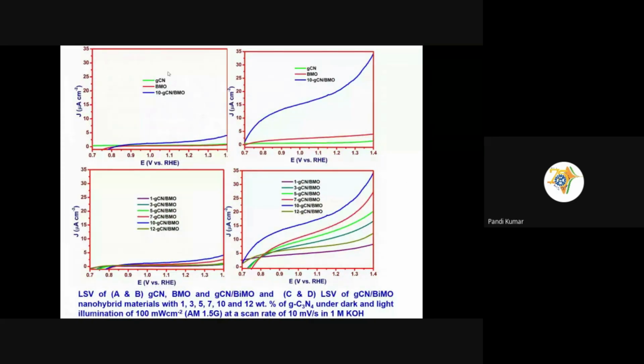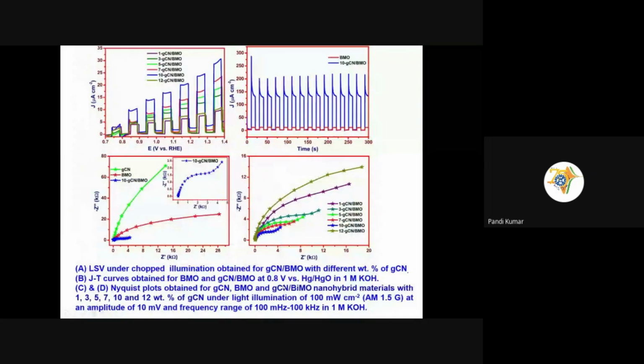So we have done the characterization in the absence of light. Just look at this. This is the control sample, and this is the variation in the samples. There is a poor response in the photocurrent, but after illumination with light, the photocurrent goes up, it increases significantly. So we have optimized 10% for higher activity over this surface.